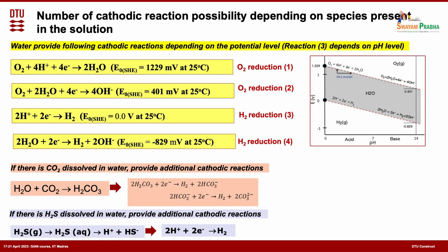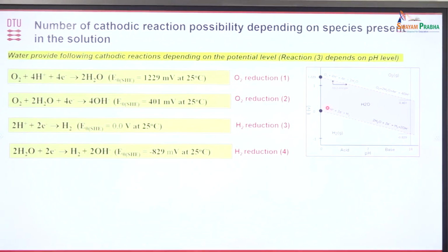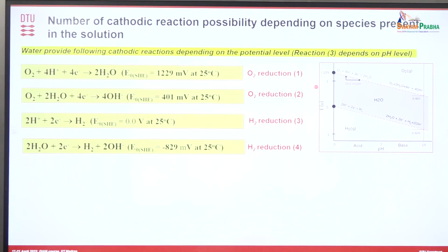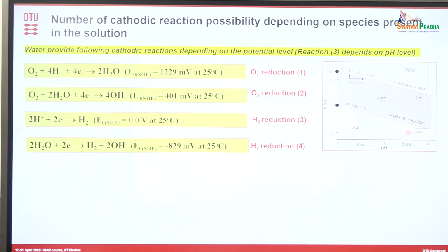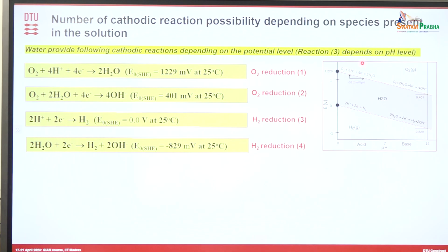Now coming to the different cathode reactions I mentioned. If you take this Pourbaix diagram, you can see that depending on where you are across this potential axis, if you take a metal like magnesium, you are here. If you take aluminum, you are somewhere here. And if you take a noble metal like gold, you are here. Those are the potential values. Depending on that, if you are cathodically polarizing, that means coming down from the potential, any of these cathode reactions can occur. You can have hydrogen reduction, which Leshan was focusing on yesterday. If you come to this level, you can have the water splitting reaction. Similarly, on the top part, there are 2 oxygen reactions where they use the oxygen. That's an important thing. Why is that important? It is the most important thing from the corrosion point of view.